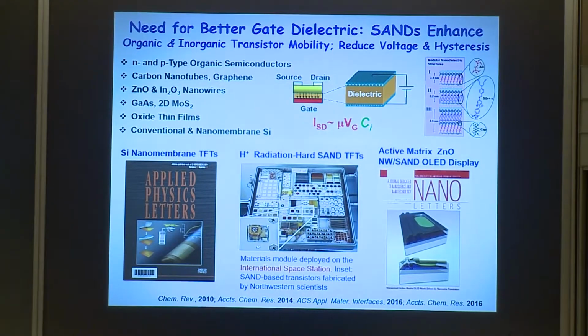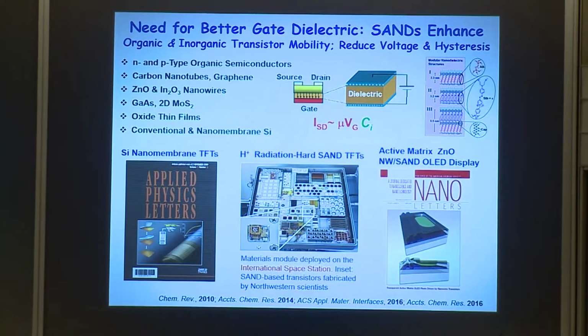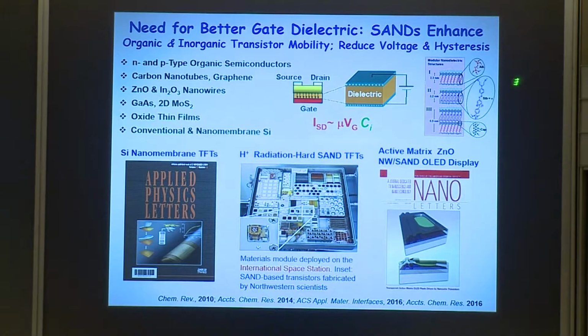And in fact, Intel ran into real problems as they began to scale down their transistors. You start getting leakage, and if you use silicon dioxide, you start getting leakage through the dielectric. So instead, they switched to a hafnium oxide compound, much higher dielectric constant. They could make the dielectric layer thinner. The problem is, for us, Intel processes at about 750, 800 C. We want to put these on plastic, and you can only imagine what's going to happen to a piece of plastic at 700 C.